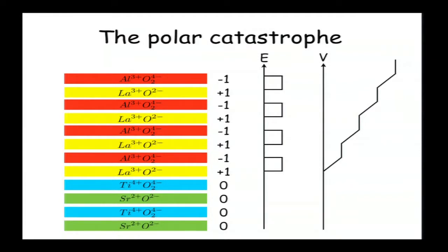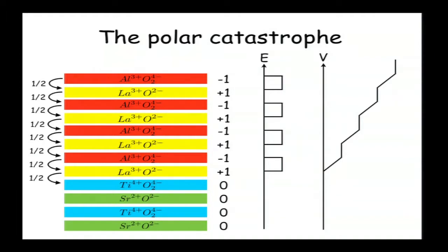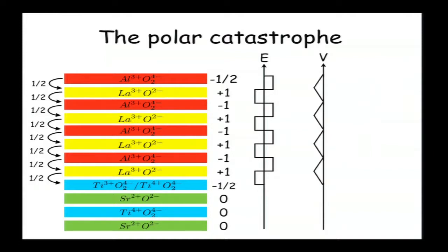In order to make it stabilize again, there is a charge that will be transferred from the upper surface to the interface. Half of the charge of the upper level will go into the interface. So now we will have, at the interface, a combination of titanium atoms with plus four and plus three. As a consequence, the electric field now is going to zigzag between positive and negative values, and therefore the voltage now is staying very close to zero. So we solve this kind of instability that is called the polar catastrophe.